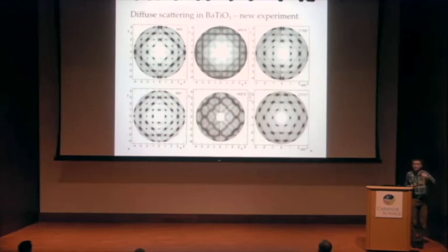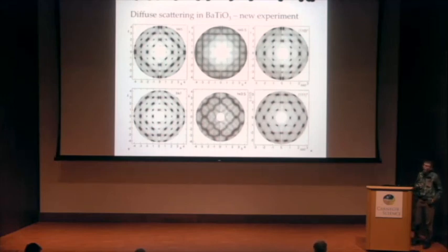After some corrections and rescaling the calculated diffuse scattering into orthogonal coordinates, you can make a cut in any direction in the reciprocal space you wish, and you really see these nice diffuse lines going through the principal Brillouin zone points. You can, for example, look at the 1-1-1 plane, and you always still see this line.